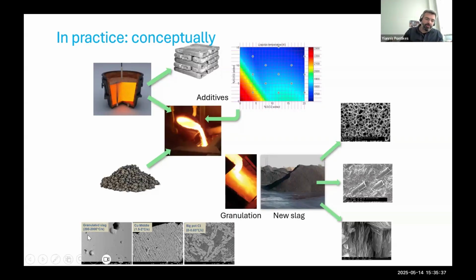You can have an amorphous or almost fully amorphous material, or a material almost fully crystalline. And this is for a copper slag we've done, modified copper slags, not the typical composition, with different cooling rates, and you find, of course, different crystal morphology. Why would you do that?